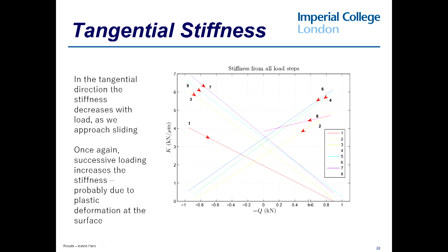It will decrease as we try and slide it, and eventually it will reach 0 when we're on the point of sliding. And then when we reverse the load, it'll pop back up to here and decrease and so on. But each time we do that, the contact is getting stiffer. Now, it's very difficult to do these experiments, and we haven't so far managed to do them for much more than a few cycles like that. But it's going to be interesting to see how that maps onto what happens if we run the contact for hundreds or thousands of cycles.